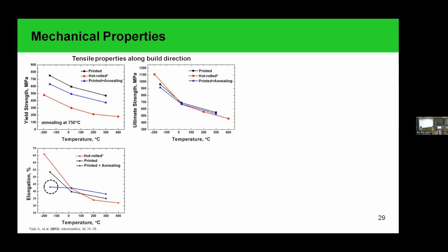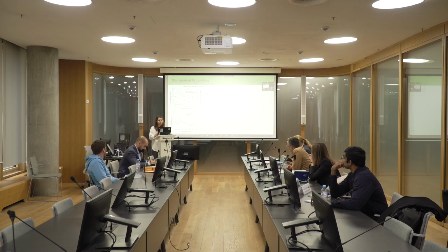Because in this case, there are room temperature and higher, and in case of cryogenic temperature, there are different deformation processes in the materials. In case of room temperature and higher, the materials deform with dislocation slip. In case of the cryogenic temperature, this mechanism is not blocked, but the twinning deformation is observed for this material at lower temperature, and possibly for this type of deformation, the formation of these brittle nitrides on the grain boundaries is more important than in case of the dislocation slip. Okay, thank you.